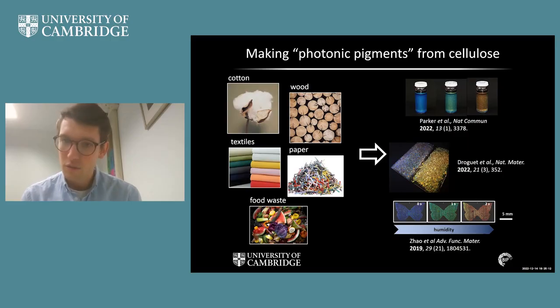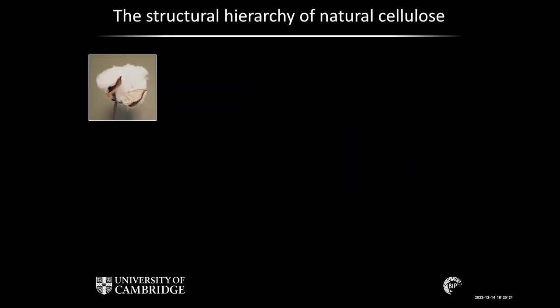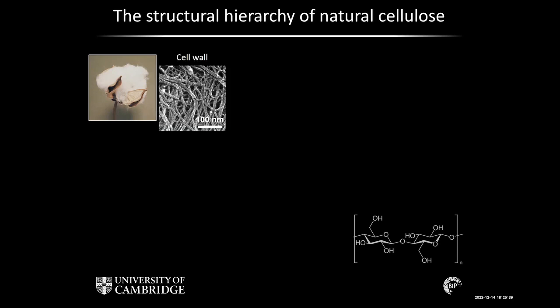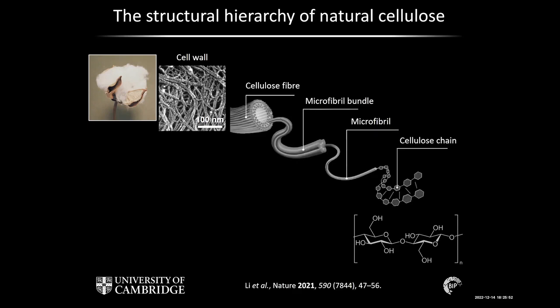And in order to do this, I just want to recap something about the structure of cellulose in these biological materials. Between the macroscopic scale, what we see of the cotton flower or wood or any other plant, and the molecular level, the structure of the individual polysaccharide of glucose, there is a whole hierarchy of different levels of structure. In particular, if we look at these cells under the microscope, electron microscopy or optical microscopy, we see that the cell wall contains a whole mesh of different cellulose fibers. And as Sylvia has already mentioned, these cellulose fibers can be shown to be made up of bundles of smaller microfibrils, which themselves are made of individual cellulose chains. And so the structure here is really hierarchical. It's like when you make a rope, you start with a single thread and you weave this into a yarn and into a larger and larger structure.